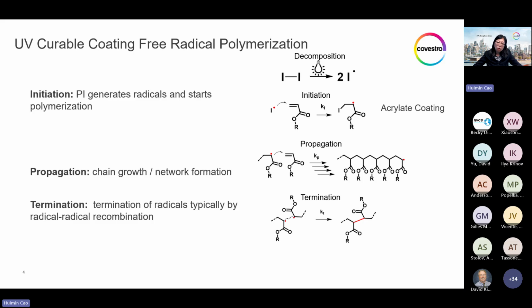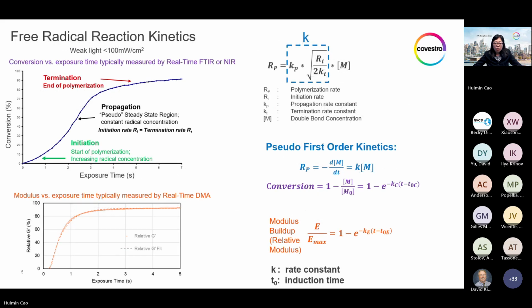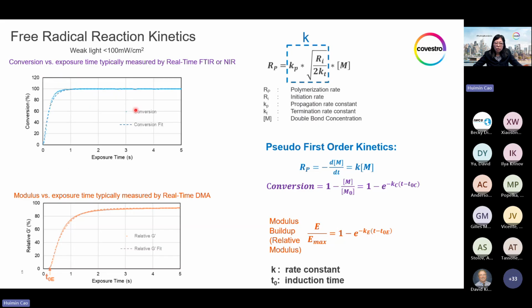And here's a quick overview of acrylic coating free radical photopolymerization reactions through initiation and propagation. And this is the main process where the chain grows and the cross-linking network forms. And in the end, termination of radicals. The monitoring of double bond conversion through real-time FTIR or near IR gives this type of kinetic curve. And this curve fits very well into a pseudo first-order kinetic curve. And here's the first-order reaction equation used to fit this curve. You can see this is a perfect fit.